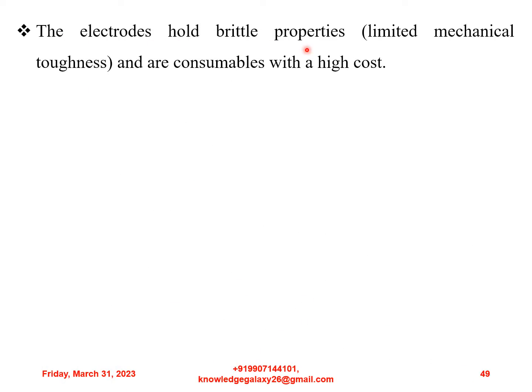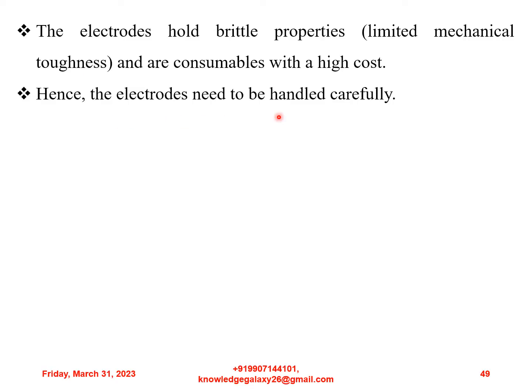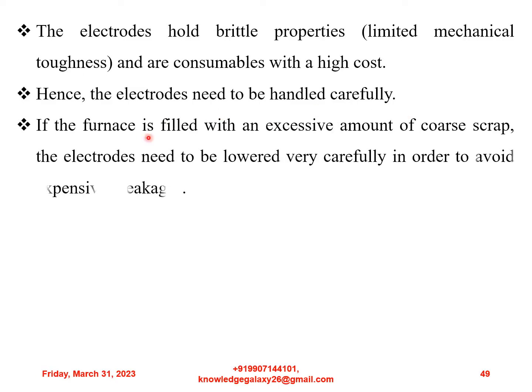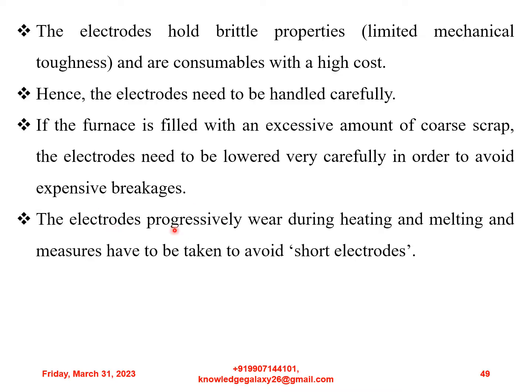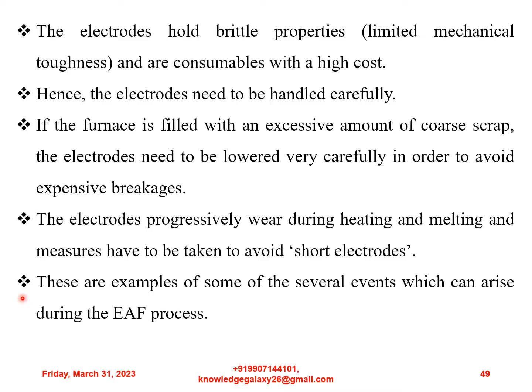The electrodes hold brittle properties, that is limited mechanical toughness, and are consumables with a high cost. Hence, the electrodes need to be handled very carefully. If the furnace is filled with an excessive amount of coarse scrap, the electrodes need to be lowered very carefully in order to avoid expensive breakages. The electrodes progressively wear during heating and melting, and measures have to be taken to avoid short electrodes. These are examples of some of the several events which can arise during the electric arc furnace process. I hope we are going so far so good and everything is clear to you all.